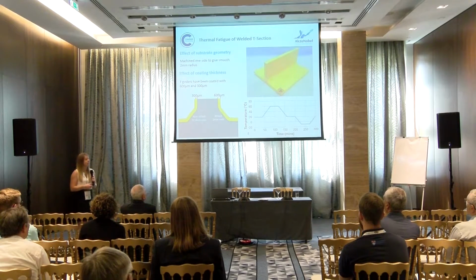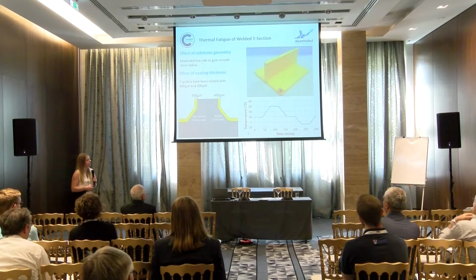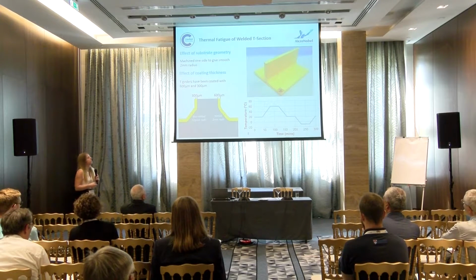This is a dry cycling profile that lasts 5 hours between 60 and minus 10 degrees C, with 40-minute dwells at 23 degrees C, 60 degrees C, and minus 10 degrees C. So this is to simulate time when there is nothing in the container, when the crude oil is being transported, and when the seawater is being transported.